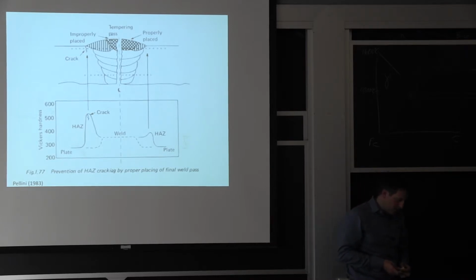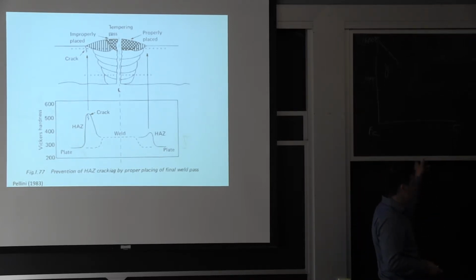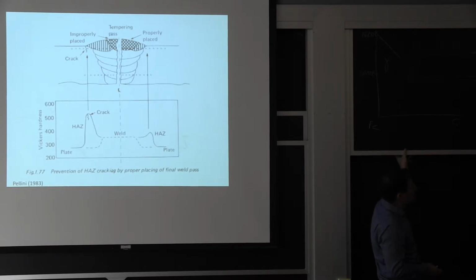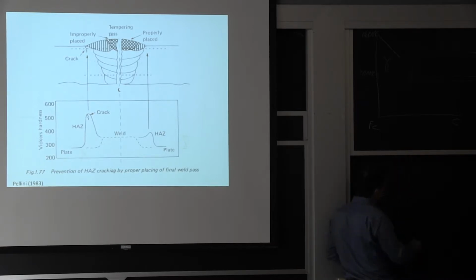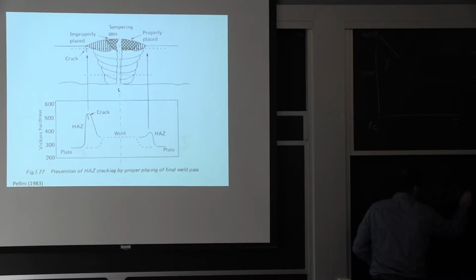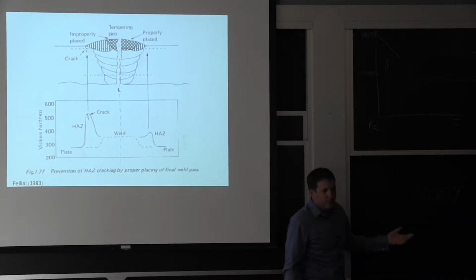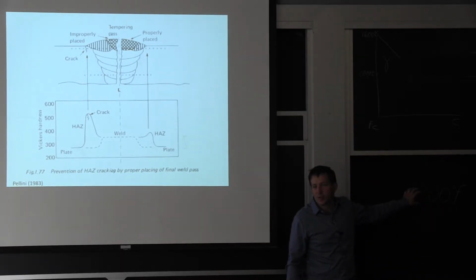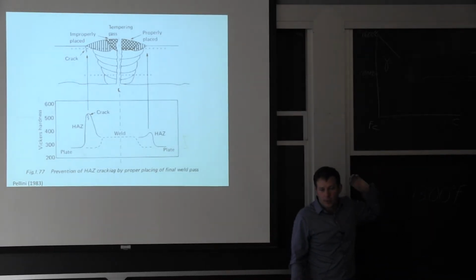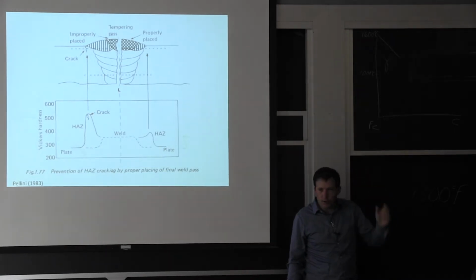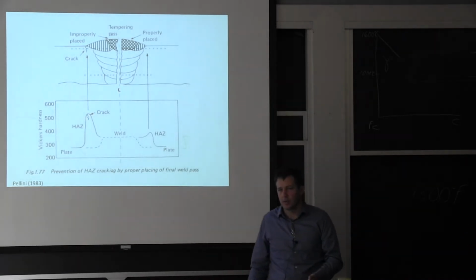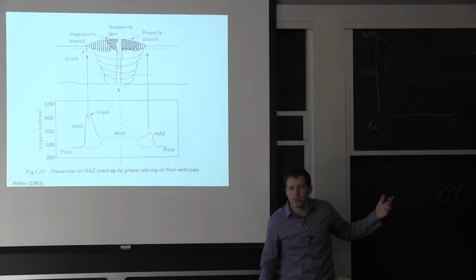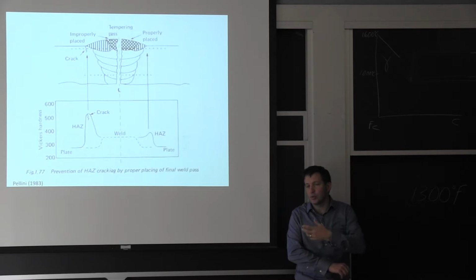And that's something that I realize we don't always teach you, or just give you some numbers, right? The stress relief temperature for steel that's typical is, I'm sorry if I'm confusing the unit because that's all I remember it in and I translated, around 700-800. So it's below the austenite transformation. Therefore, if all you want is to relieve stresses from the weld, you can go to those temperatures. Now, if you form martensite, at those temperatures you're also going to temper it. So you're really doing both in this case.